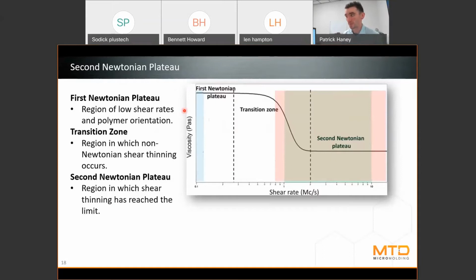So this is another plot that I'm sure many of us are familiar with, viscosity versus shear rate, right? And it describes a concept that we've been talking about, right? The harder we push a non-Newtonian fluid, the easier it flows, okay? So the first region is the first Newtonian plateau, and this is a region with low shear rates and low velocities, right? Where we don't have a lot of influence from orientation or free volume, and the entanglement is very high. So we don't see a lot of drop in resistance to flow at lower shear rates because we're not pushing it very hard at all.